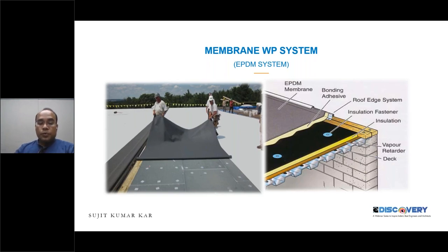So that's why, if you would like a fully bonded system, then two types of adhesive are nowadays used. One is the bonding adhesive, for better bonding of the EPDM with the concrete substrate, and another is called the splicing adhesive. This adhesive is recommended for the overlapping sections between the two membranes. So these are the systems we are recommending for the exposed areas where EPDM membrane is being applied.